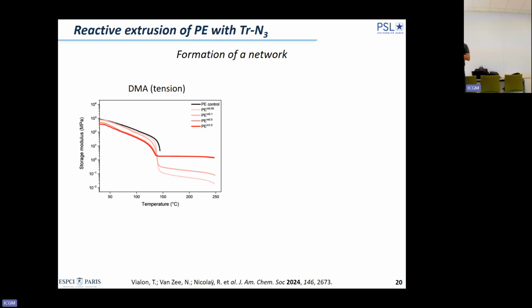So if we go to a system which is homogeneous, which we did, either with the same molecule, different polymer, or different molecule, then we don't see cross-linking because they undergo hydrogen abstraction and grafting, and they don't have time to react together, or they don't have the opportunity. So even though I'm rushing, it's very important in our case to have a phase-separated system. But because of phase separation, there is a threshold. If you increase the amount of additive, you are not going to increase the apparent cross-linking density.